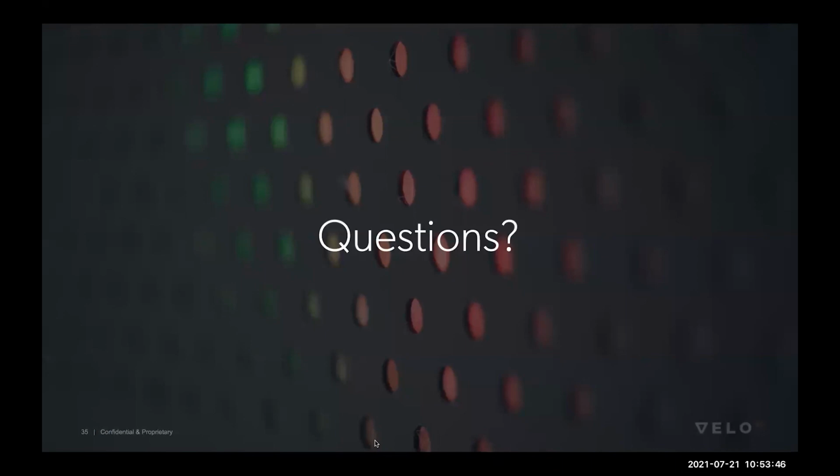It's a question we get a lot, and we have some unique testing characteristics and testing data based on these criteria that are usually driven by the customer or the end user. We have quantified that data based on certain levels of overhang, levels of different low angle skins, and I can share a data set if someone is curious as to what that means, but we don't see a big degradation for material properties in these low end. That's based on tensile data and fatigue data.